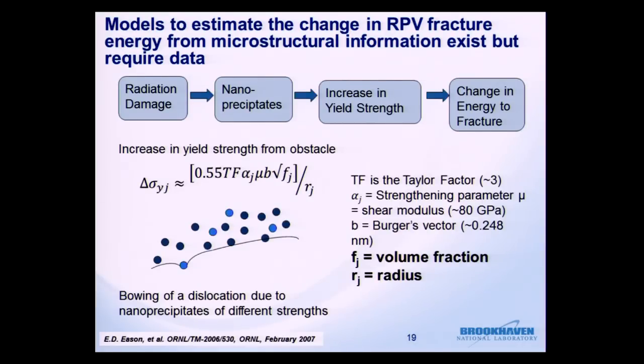Models already exist to estimate the change in the RPV fracture energy from the microstructure of the material. So we have radiation damage, which leads to the formation of nanoprecipitates, which leads to an increase in the yield strength in the material. And in this case, an increase in the yield strength is a bad thing because it limits the ductility and pushes the material towards brittle failure. And from this increase in the yield strength, we're able to predict a change in the energy to fracture.